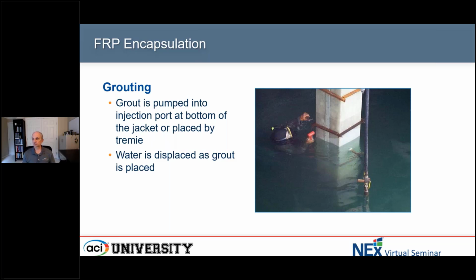And if you look closely at that photo, you'll see a darker shade just above the waterline, and then you'll see a lightish gray shade of material just above that. That darker shade is the water that's being forced out, and the lighter shade of gray is the grout as it's being pumped in. So you can actually visually monitor to a certain degree what's going on behind that jacket as the grout is being placed.